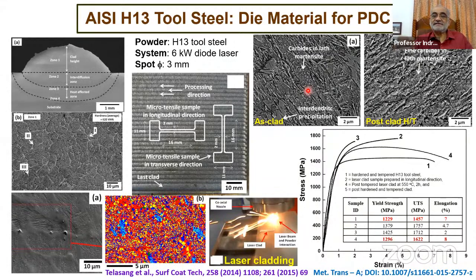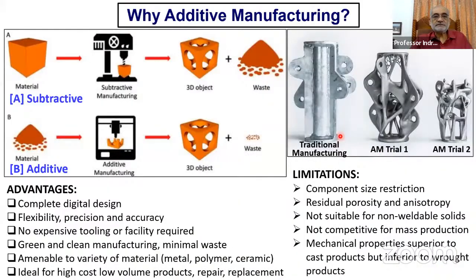And since now the lath size is finer than what could happen in a bulk, because it's happening only within 1 or 2 millimeters with a very fast self-quenching, the platelet size is much smaller. And as a result, we get not only higher strength, but also higher plastic region. So just 1 or 2 things about why we are interested in additive manufacturing: purely because if you do subtractive, you create so much waste. If you do additive, practically no waste.